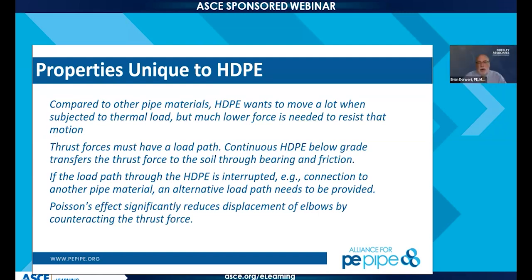Well, if this is installed in an open trench and then backfilled and compacted, there's really not a lot of change on the strength. It's going to pretty much stay fairly constant, and the soil is going to have enough resistance in it where even if you were to assume a fairly long frictional debonding, that strength is really not going to be exceeded. And you've got to look at it in terms of stress and strain and strength. They're all interrelated. Well, if that pipe shrinks, it's going to create strain in the pipe, which is going to create a stress, which is your thrust restraint or your anchorage restraint value. So does that really change?